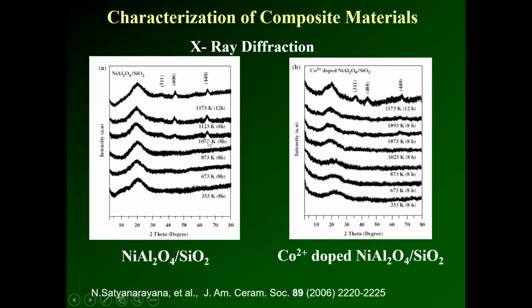Only at 800 degrees centigrade, that is 1073 Kelvin, some peaks start coming, and they grow with increasing temperature. So crystallization takes place. When we analyze these peaks, they are in the nickel aluminate phase. So the crystalline phase of nickel aluminate is formed. So thermodynamically, this much, 800 degrees centigrade, is required for the ions to form nanocrystals, or nucleation starts.